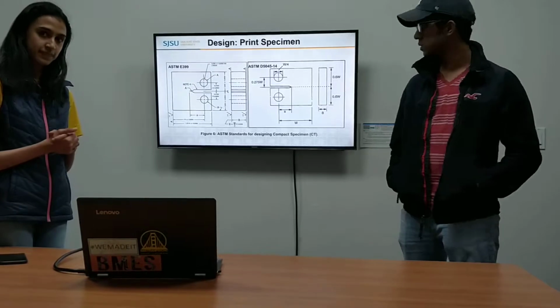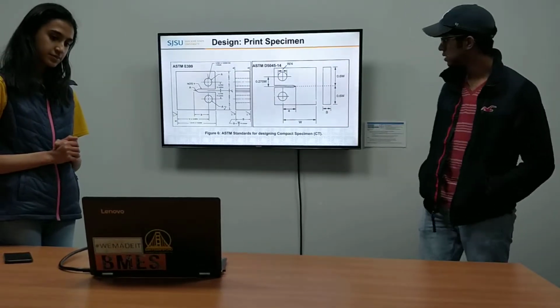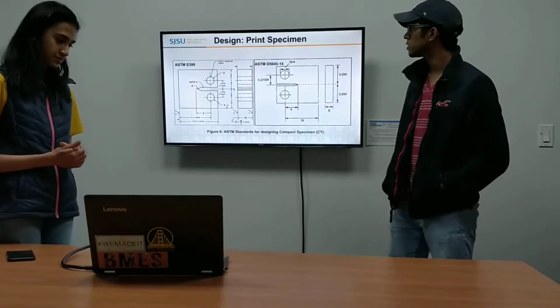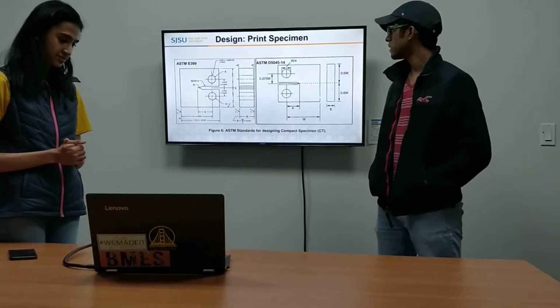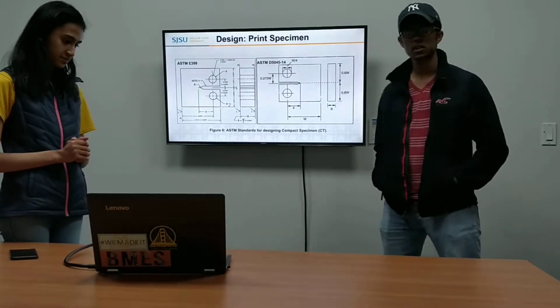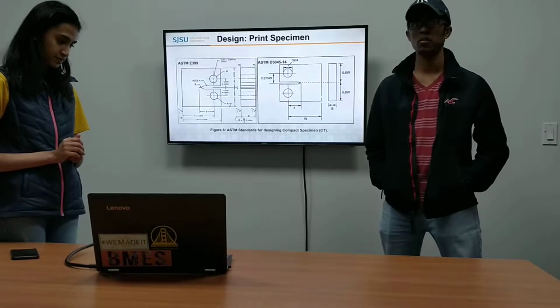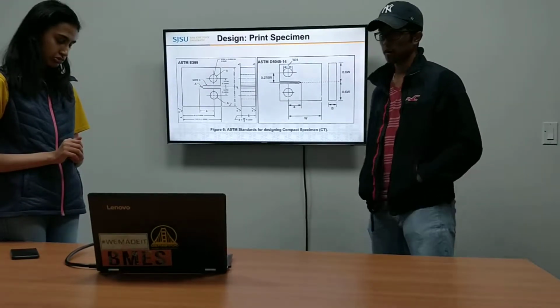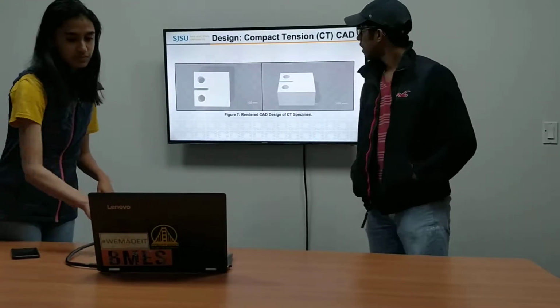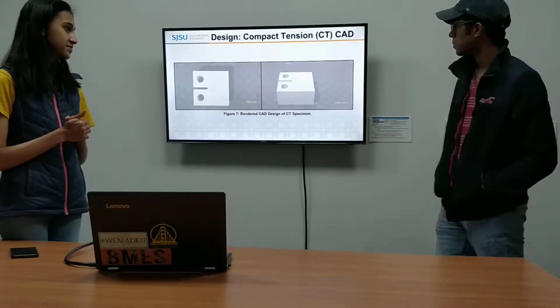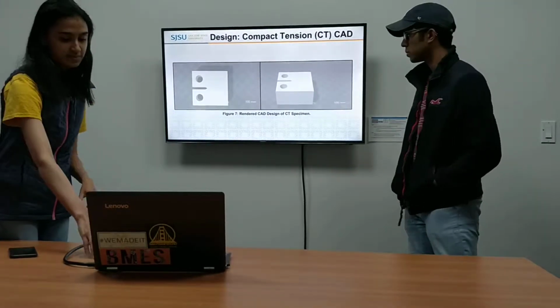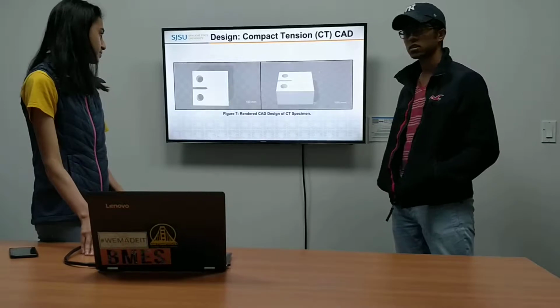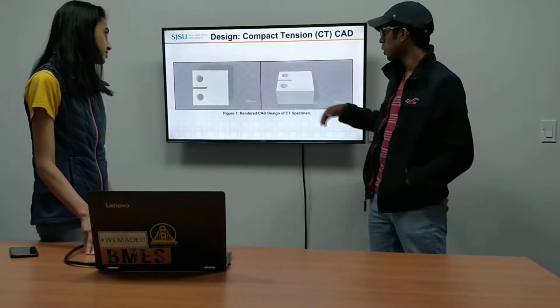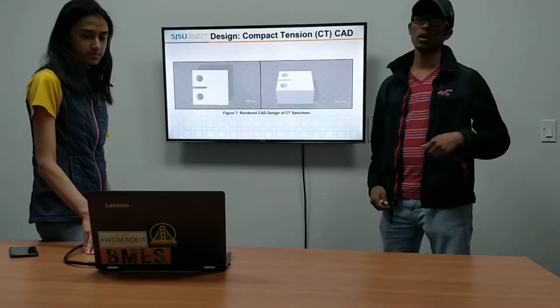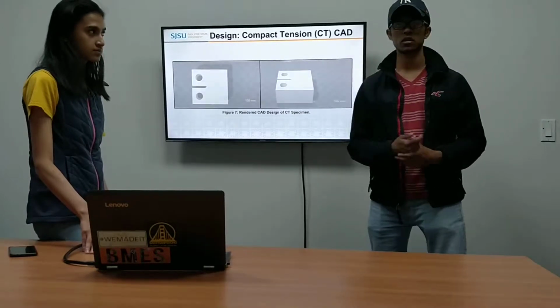The design of our specimen is based on ASTM standards, and especially E399 and D5045 were used to design the specimen in SolidWorks, and that's what was used to print all our specimens. This is just a schematic representation of our specimen, which is a block with a pre-manufactured crack in it, and the 2 holes will be used by the Instron to pull apart and induce the crack propagation.